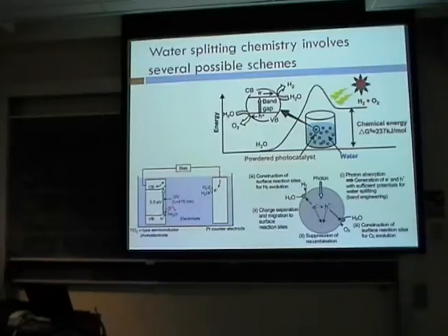So you have the water going to form oxygen on this semiconductor device, and titania actually isn't a very good catalyst for this reaction anyway, and other semiconductors tend to not be a very good catalyst for this reaction either. And so you would just use an electrocatalyst that really isn't a photoactive material on this side, where you're just using the driving force for this reaction to make electrons flow through here to do the standard hydrogen evolution reaction, so making hydrogen from protons.